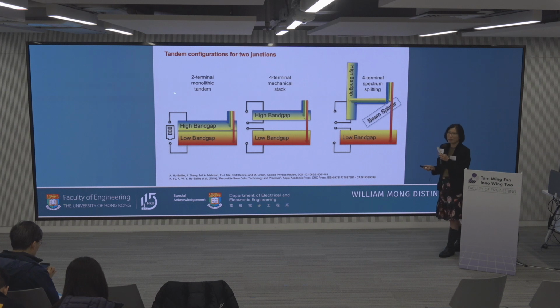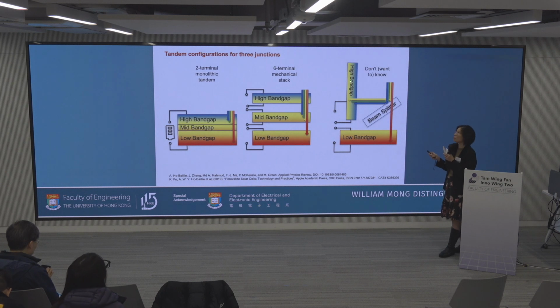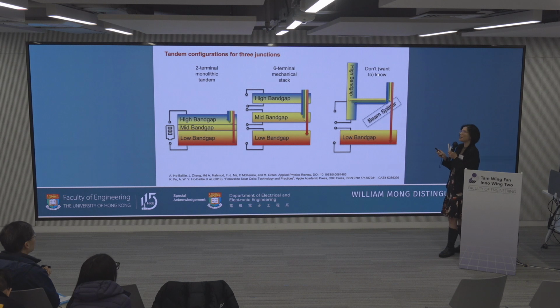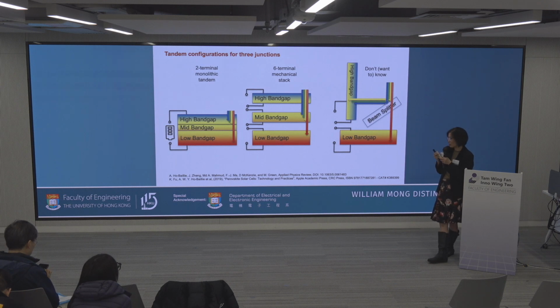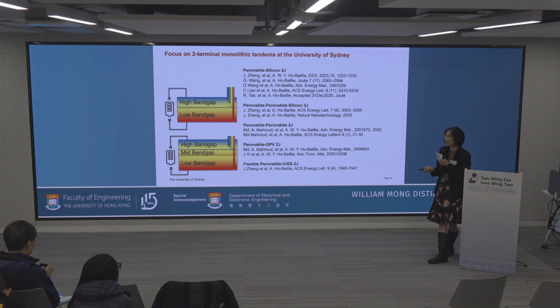So how do you build a tandem? You can grow, you can deposit the high bandgap material and low bandgap material, or you can just mechanically stack them so the electrical connection is independent, or you can divert the sunlight onto the high bandgap or the low bandgap. So that's okay for 2-junction, but as you move to triple junction, you can see that it gets more complicated, and we don't know or don't want to know how to do that in that configuration. So for triple junction, you get the 6-terminal, and monolithically, you still keep the 2-terminal configuration, which is quite elegant, and therefore our group has always concentrated on the monolithic tandem.